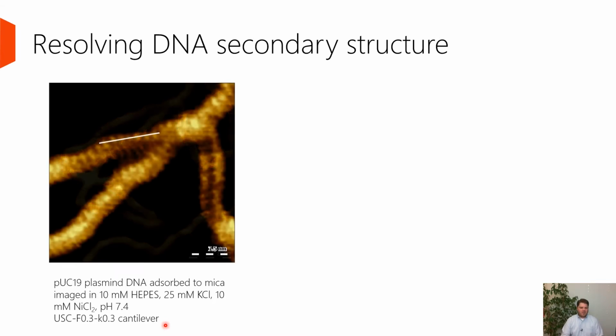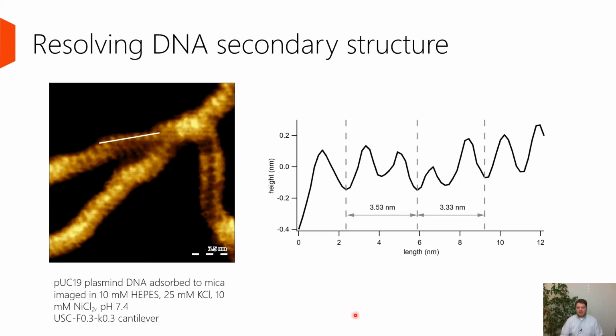You can see this ripple banding, which indicates that this could be a secondary structure element, or the secondary helix of the DNA. Now, if we zoom in, we can take a cross section across a piece of the DNA, and if we then look at it, we see these hills or peaks and these valleys, and measuring the distance between every second of these, we come up with an average distance of 3.4 nanometers, which indeed corresponds to the pitch of a double helix in the B-DNA structure, which is very well established by crystallography. So we are pretty confident, also looking into literature, that what we see is indeed secondary structure of DNA. And this is, as I said, not the easiest measurement to do.